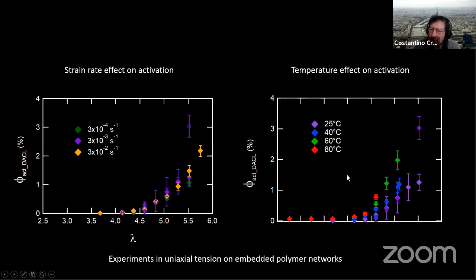We see an increase. If we look at the 80 degree sample, the sample breaks sooner, so we don't have as many points, but at 60 degrees, you can see that there is a difference in activation. So indeed the material, the bond itself activates a little more when you increase the temperature, but it would even increase the difference that we're seeing in our fracture experiments and the rate dependence during the fracture. So the answer there is indeed, we don't find unphysical results, but they certainly do not explain our fracture results.